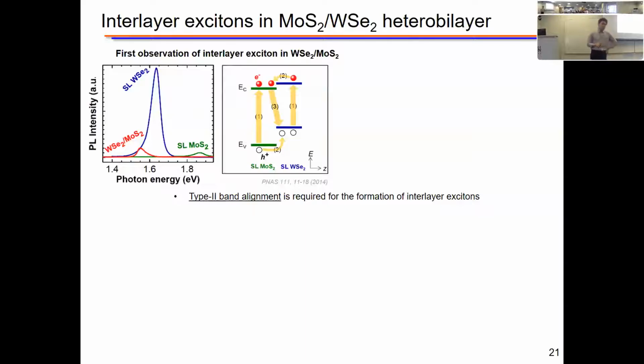The mechanism they reported in the paper was that first, the constituent monolayers absorb the photon energy and create this electron-hole pair. Because of the band offset in this type 2 band alignment, the electron and hole drift to the atomic interface, and they recombine into an interlayer exciton. This platform has been of real interest because we can study the charge collection and charge separation mechanisms, relevant to photodetectors and solar cells.